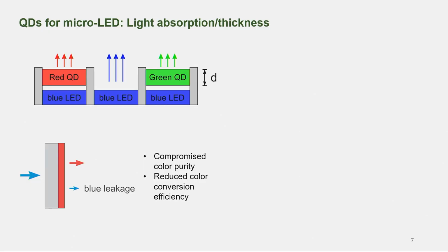So first, why we care about the absorption coefficient, how it absorbs light. Basically, if you have, let's say, a blue LED as a light source and a quantum dot conversion layer on the top, if it's very, very thin, then it doesn't absorb enough light, and you have blue color leakage. This will compromise your color purity and reduce color conversion efficiency.